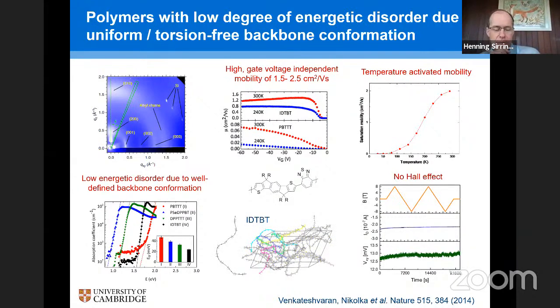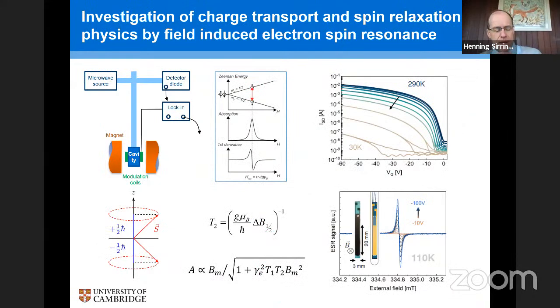We see that, for example, in the optical absorption, the Urbach energy of some of these polymers tends to be on the order of 20-25 millielectron volts, which is about the same as what you would have in an inorganic gallium nitride crystal. So it's quite astonishing that despite this structural disorder in these systems, you can make such energetically and electronically clean polymeric systems. And so it's interesting to understand transport physics, and one of the tools that we've used in the last few years, as part of this synergy project that Jairo mentioned at the beginning, is to use electron spin resonance spectroscopy to understand the spin relaxation behavior of these polymeric systems, and then relate the spin dynamics to the charge dynamics.